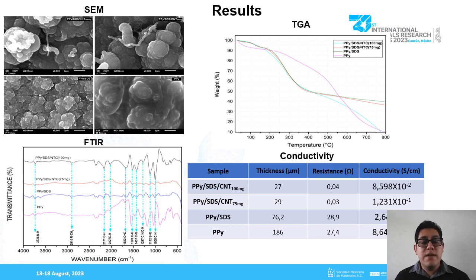The TGA analysis reveals that the polypyrrole with SDS and 100 milligrams of carbon nanotubes, and polypyrrole films lose the most weight during the test. After 200 degrees Celsius, polypyrrole with SDS and with 75 milligrams of carbon nanotubes and polypyrrole with SDS become more stable. Beyond 200 degrees Celsius and up to 550 degrees Celsius, polypyrrole is more stable. And finally, after 550 degrees Celsius, polypyrrole with SDS and with 75 milligrams of carbon nanotubes and polypyrrole with SDS films are even more stable, maintaining higher weight percentages.